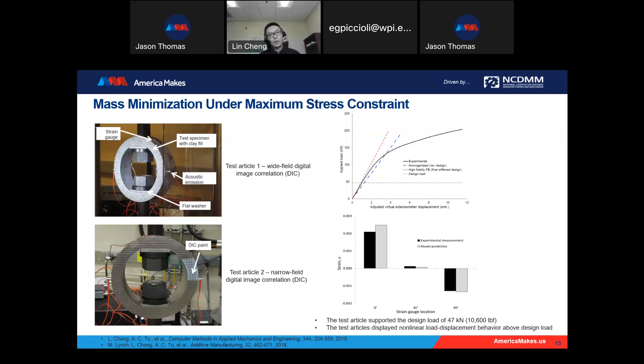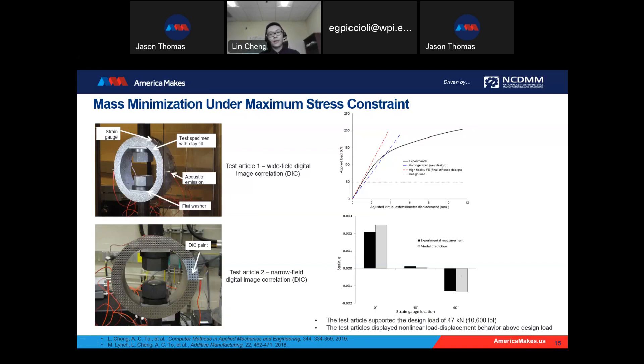Additionally, we attached three strain sensors at 0 degrees, 45 degrees, and 90 degrees to compare the measured strain with model predictions. We get pretty good agreement, which means the proposed homogenization model and optimization give us good predictions for performance and mass minimization of the overall component.